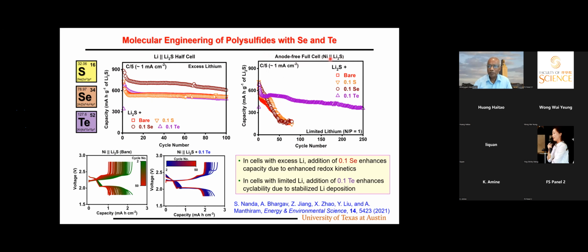So this is similar to a lithium-ion cell, except you will have graphite here. The cells are assembled in the discharge state. So we are going to compare these two configurations. First with the Li2S cathode alone, then the second with 10% sulfur addition to that, 10% selenium addition to that, 10% tellurium addition to that. If you look here, selenium addition obviously helps to increase the capacity.